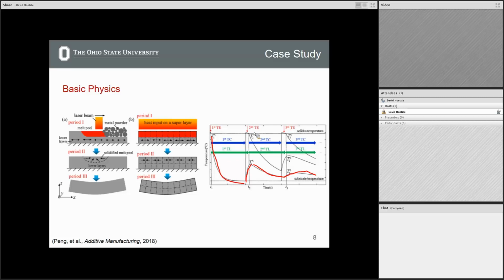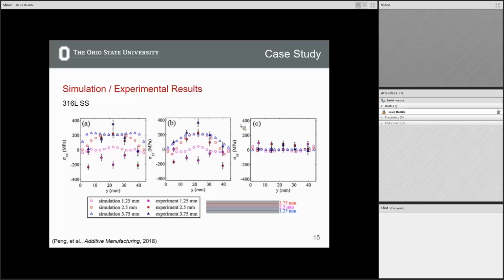And that's a much more computationally tractable way of trying to understand and characterize these deformations than if you do a full spatial temporal finite element mesh. So the full spatial temporal finite element meshes, if you want to do this for the part, it's going to take you multiple days. We were able to, by making some simplifying assumptions, get answers on the order of just a few minutes, actually, in terms of what the distortion and stress in the part would be. So what this enables us to do, if you have a model and you can have somewhat reasonable validation of that model with experiments, you can start to look at, all right, how can I use this for design?